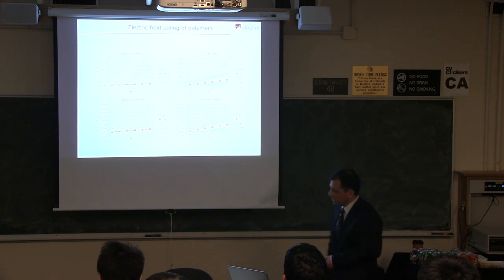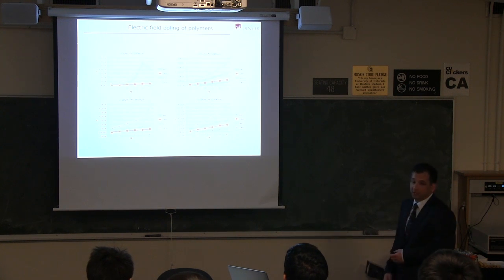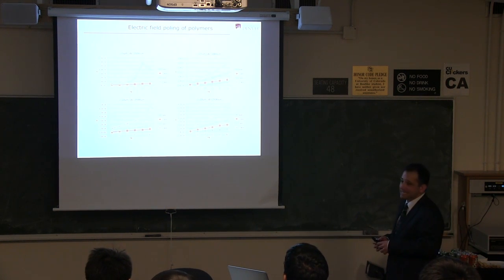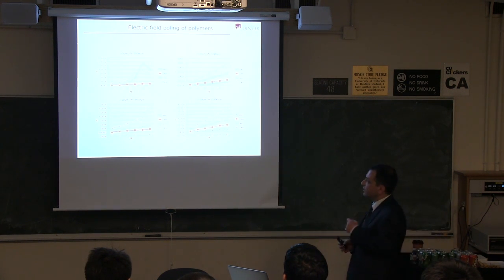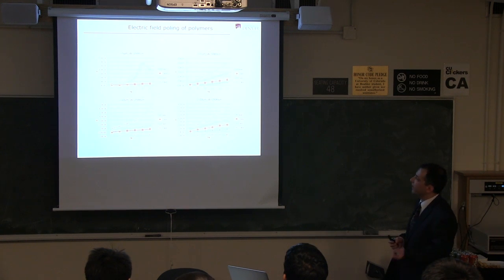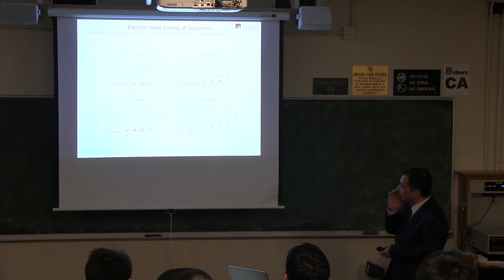There is a frequency response to this, so this is done under AC. We're using the AC susceptibility of the organic material. So it's not a DC poling. DC would not be strong enough field. But the AC susceptibility can be very high, and we're finding there is a frequency dependence.